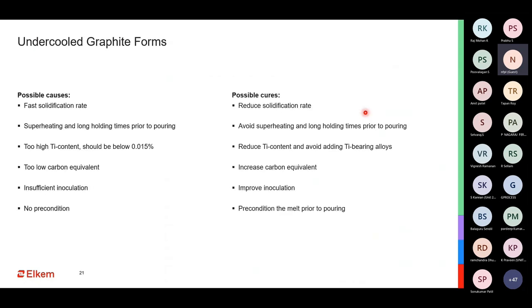Why do you have undercooled graphites? Because we have a much faster solidification rate and the carbon does not have enough time to come out as graphite. Why does this happen? When we have higher superheating and a very long holding time, we kill the graphitization potential and thereby the graphite coming out tendency goes down. When we have too high titanium content, which again reduces graphitization, when we have a very poor carbon equivalent, meaning there is not enough graphite to come out, when we have insufficient inoculation and when we do not precondition the metal. These are some of the possible reasons due to which we get undercooled graphite.